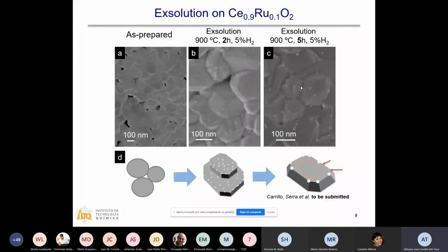So to answer that question, yes, we can actually exsolve metal nanoparticles from a fluorite structure such as ceria. Here, what we use is ruthenium-doped ceria. We thought that ruthenium could be a really good catalyst for this application. If you compare the as-prepared image with the SEM images after the exsolution treatment, you can observe that after 2 hours of exsolution treatment at 900 degrees Celsius, there is the appearance of these tiny nanoparticles that are covering the surface of the cerium oxide. If we increase time, we also increase the size of the particles, and they tend to grow more on the edges of the grains of the cerium oxide.